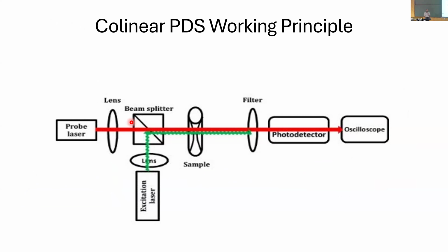Now what happens here is the excite and the probe laser both are in the same direction, overlapping inside your sample. So the interaction of these two lasers is happening inside the sample, and again the same principles apply, and you can measure liquid samples. We are basically modifying a tool to do this and then evaluate certain things.